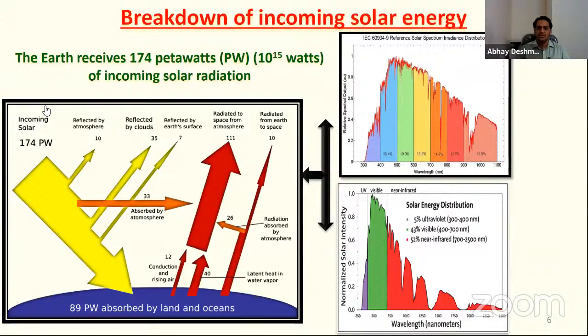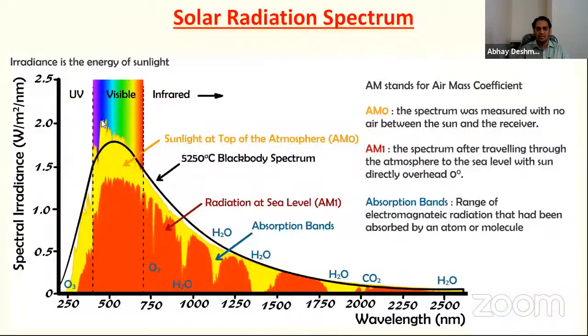And if you again break down from 300 to 1100, which is basically the bandgap of a silicon solar cell, we have around 18.4% over here, 19.9% in the 500 to 600 range, 18% in the 600 to 700 range, and so on. So why is this breakdown important? Because how much energy you can absorb depends on the bandgap of your material. So depending on this breakdown of energy, you can modulate your device and play around.